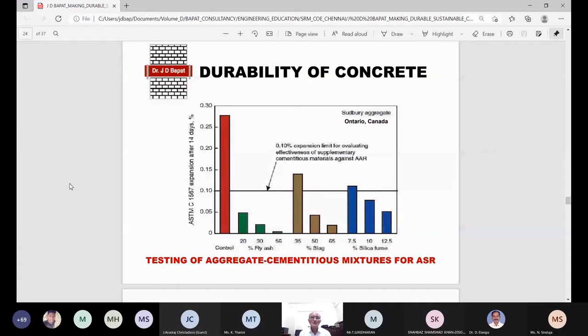Okay, so you can see in the control concrete, the expansion is actually crossing the limit of 0.1, which is fixed by the ASTM C1567. This ASTM C1567 is also called the accelerated mortar bar test, AMBT. And you can see that fly ash, slag and silica fume reduce the expansion after 14 days. In all cases of fly ash addition from 20 to 55%, the expansion is much less. In case of slag also, above 50%, it is satisfying the requirement of ASTM. Silica fume also, above 10%, is satisfying the requirement of ASTM. Right? We'll go to the next slide.